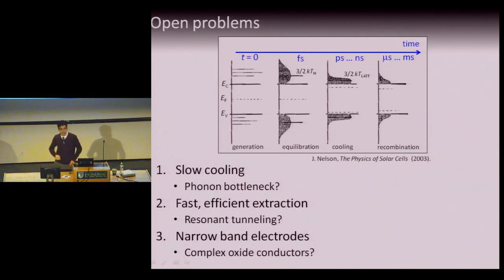Then what happens is that these charges collide with the ions in the lattice, generate phonons, in other words heat, and cool themselves down. This is the cooling process. This happens on a time scale, depending on the material, that ranges from picoseconds to nanoseconds. And in that time scale, you have the cooling from close to the temperature of the sun to something close to the temperature of the Earth.